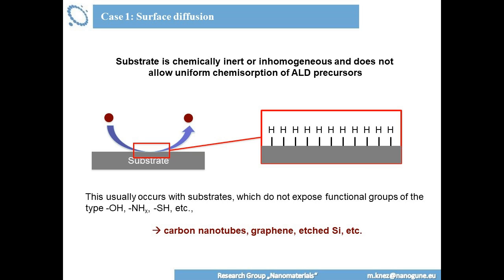The chemistry which you learned about yesterday is a very important point to grow coatings. However, the most critical point in order to grow a film on top of a substrate in ALD is to have functional groups where the precursor can attach. This is something which I think is self-explaining and easy to understand. However, what happens if you have a substrate which in some way is inert? Inert in the sense that there is no chemical functionality, so your precursor cannot bind.